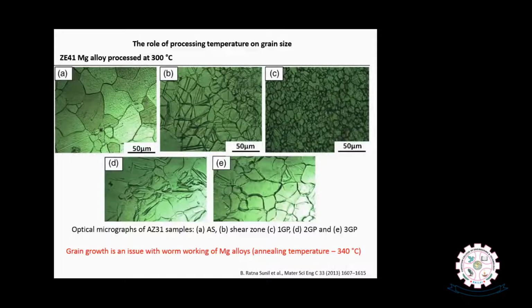So that indicates the processing temperature plays very important role in retaining the microstructure refinement that we achieved after groove pressing. Because at room temperature, deformation of magnesium is very difficult. Anyway, we have to heat at higher temperatures to process. When you are heating to certain temperatures which are close to the annealing temperatures, whatever the advantage or the benefit that we yield from the plastic deformation, severe plastic deformation to achieve grain refinement, that we may lose because of the annealing effect. So care must be taken in selecting the processing temperature of magnesium alloys if achieving grain refinement and retaining the grain refinement is the prime objective.